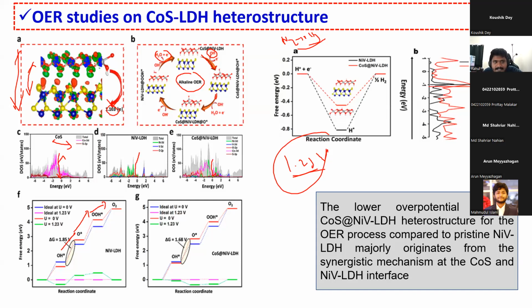And this is for the pristine nickel vanadium LDH. For pristine nickel vanadium LDH, the highest energy step in this conversion is the OH to O step, with a higher barrier of 1.85 volt. But when we made a heterostructure, we found that this value reduced to 1.68. That means after the formation of the heterostructure, because of the synergetic interaction between the substrates, it can easily convert OH to oxygen.